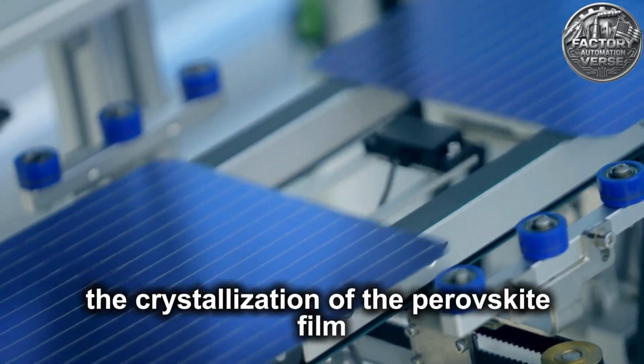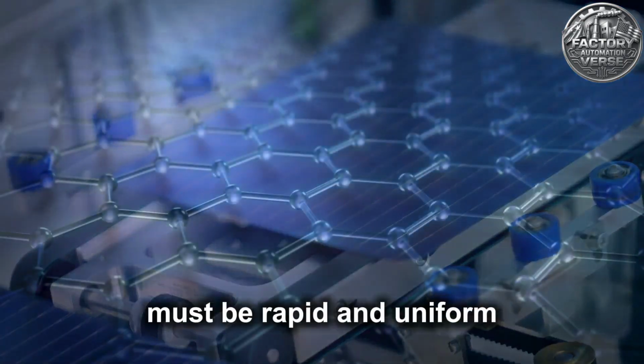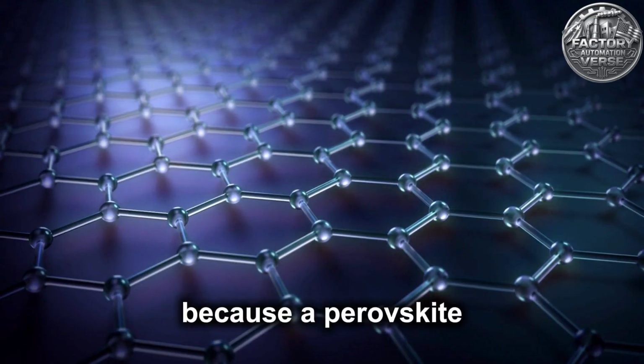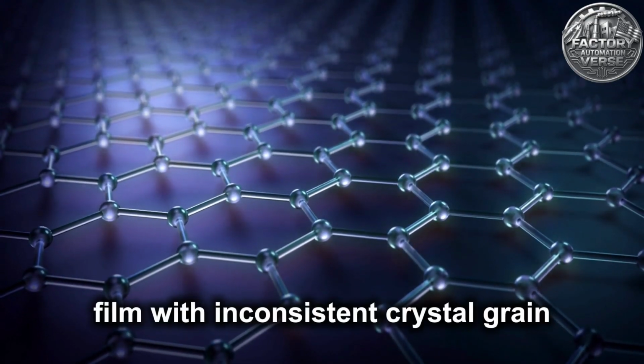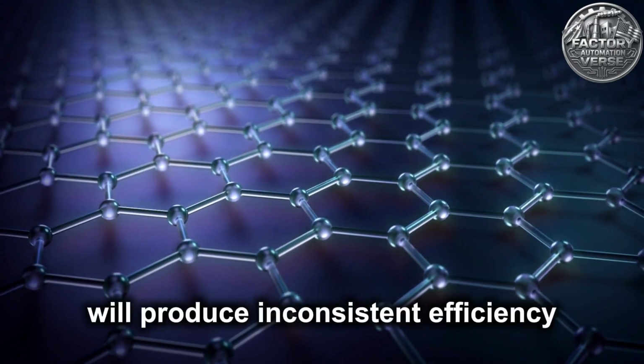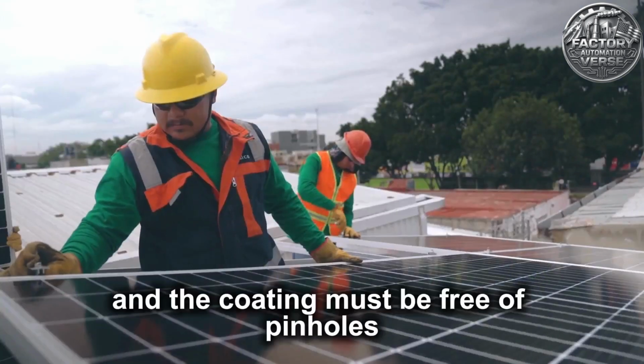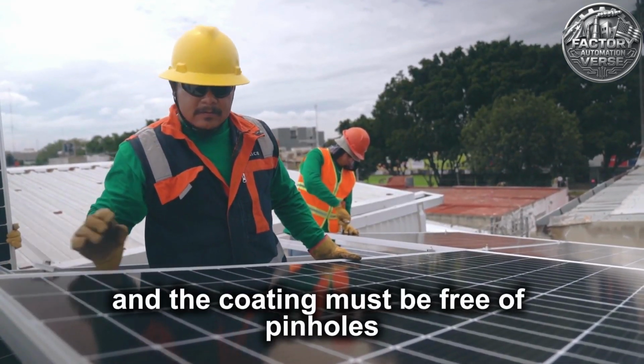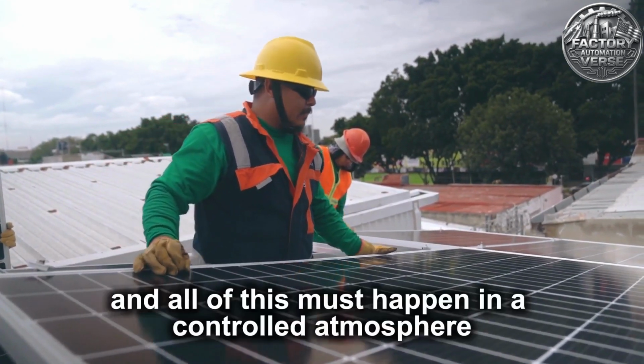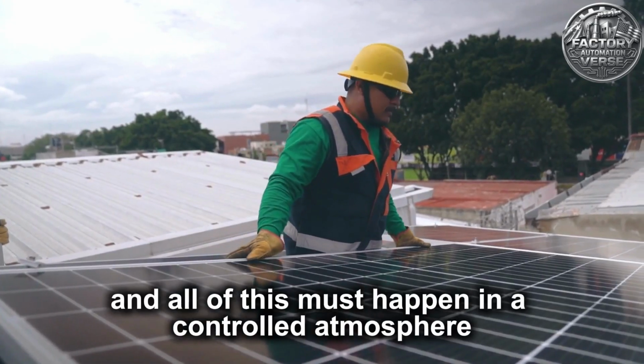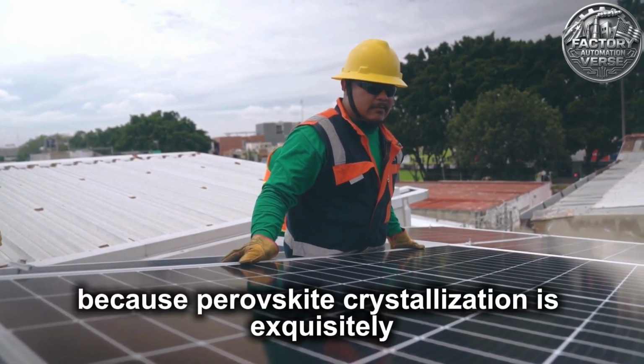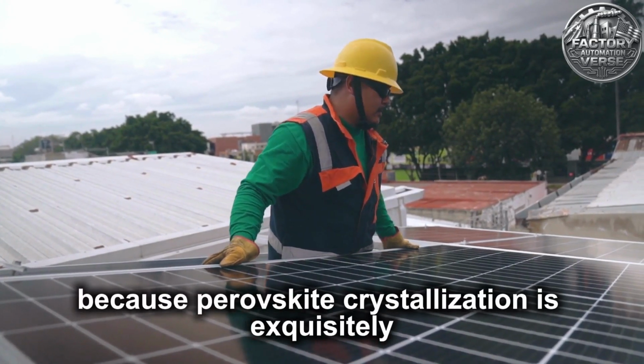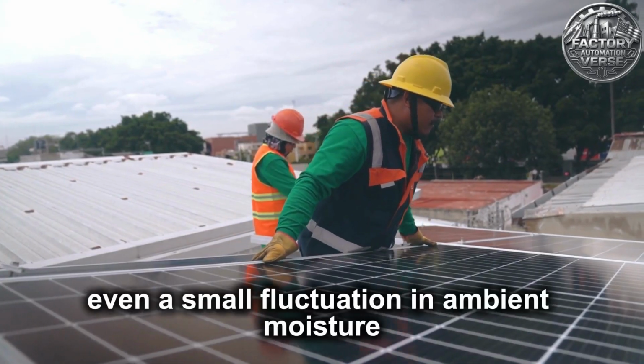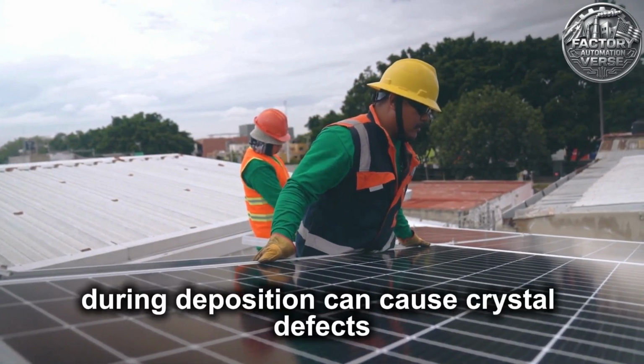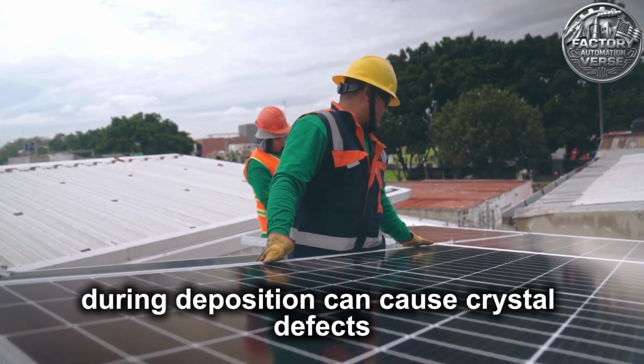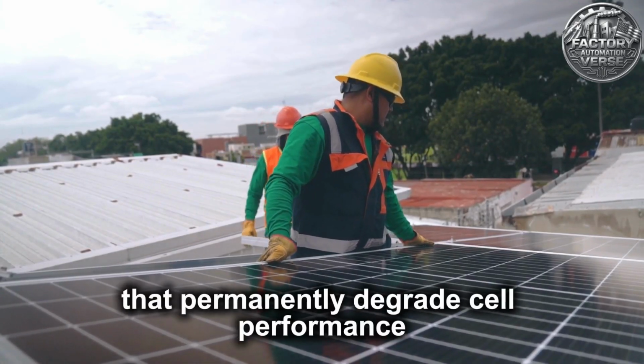The crystallization of the perovskite film must be rapid and uniform, because a perovskite film with inconsistent crystal grain size across its area will produce inconsistent efficiency, and the coating must be free of pinholes that would allow electrical shorting. And all of this must happen in a controlled atmosphere, because perovskite crystallization is exquisitely sensitive to humidity. Even a small fluctuation in ambient moisture during deposition can cause crystal defects that permanently degrade cell performance.